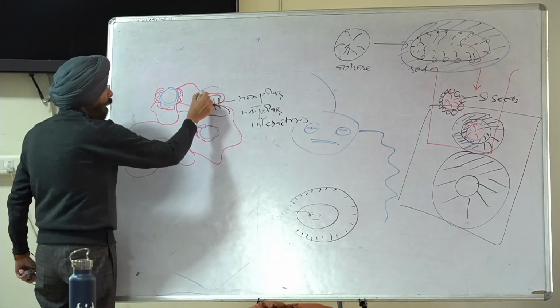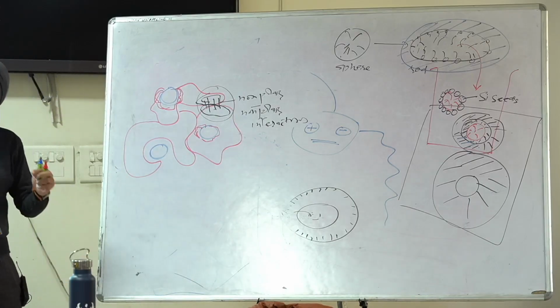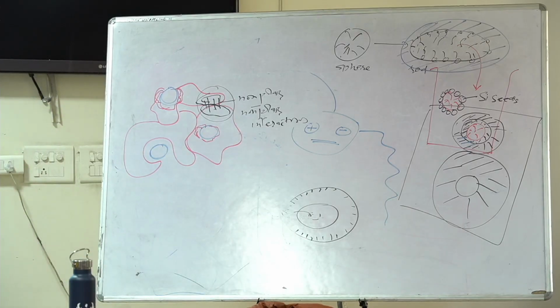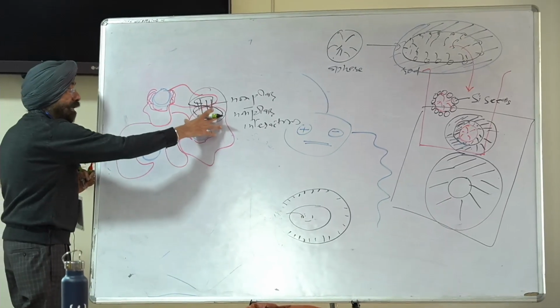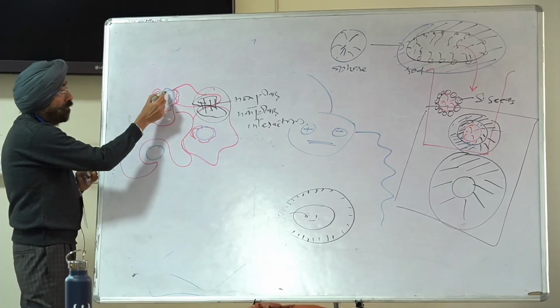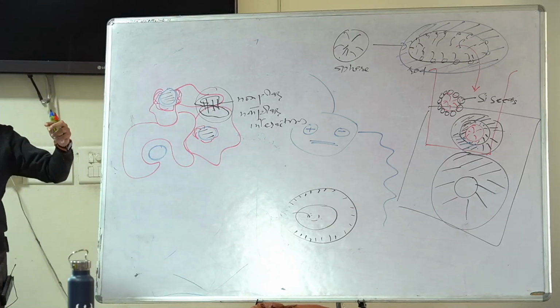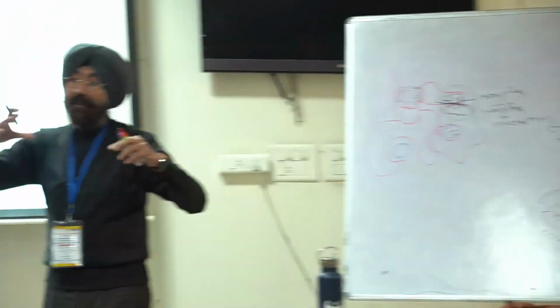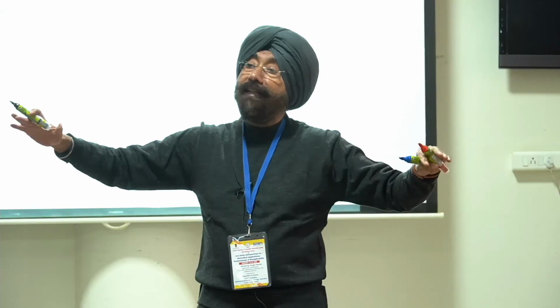These non-polar hydrophobic interactions through the hydrophobic domains of adjoining protein molecules are very intense, right? So therefore, you see that this protein macromolecule is attached because of the nanoparticle. It helps to bind the protein molecules and to create a reinforcement in the form of a protein film.